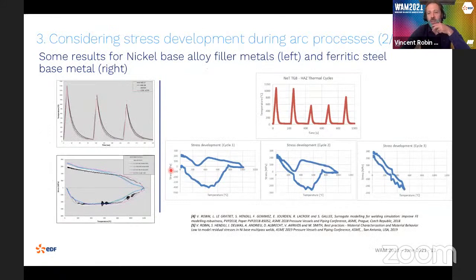You have here some examples of experimental results for two kinds of material. One without phase transformation, which is a nickel-based alloy, on the left. So you can see compressive stress at heating and tensile stress at cooling. And one other with a phase change and volume change due to bainitic or martensitic transformation during cooling. And you can notice that during this transformation, the volume change modifies the stress evolution.